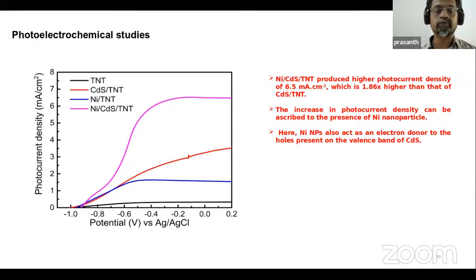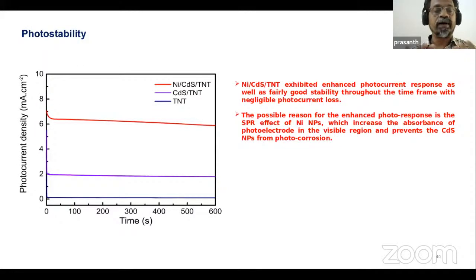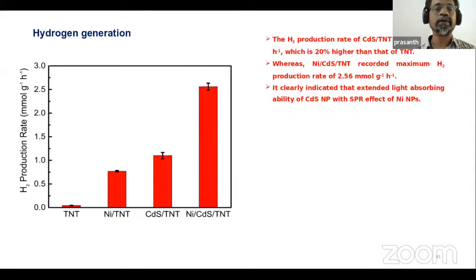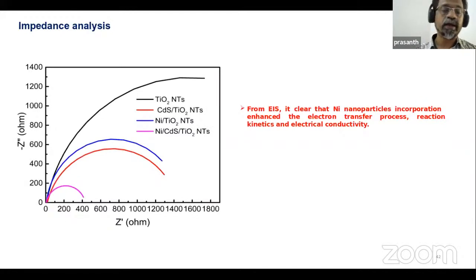It means more light absorption, which means more photocurrent can be generated with this electrode system. The stability of the electrode is also better, and the hydrogen production rate can also be enhanced with this electrode. And you can see the impedance is considerably decreased by including the nickel nanoparticles in the electrode system.